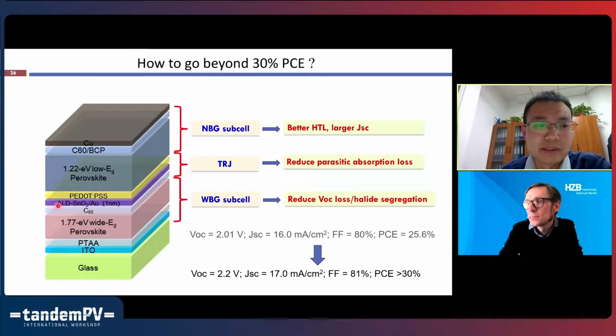So we have to find a good processing condition to make sure the layer is very conformal on the surface of the top cell, and also very compact. Usually after making about 20 nanometers of this tin oxide layer, we can meet those requirements, and we can do spin coating of the PEDOT without any problem. And of course, also for the narrow bandgap perovskite. So if you find that after deposition or spin coating of the PEDOT layer the perovskite is not damaged, then you can easily do the following layer of the narrow bandgap perovskite, I think. Yeah.